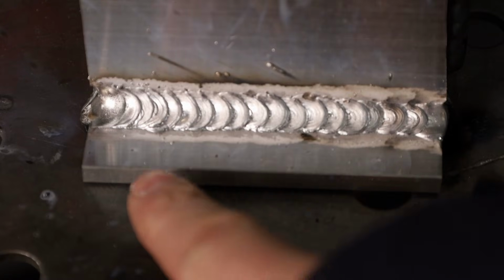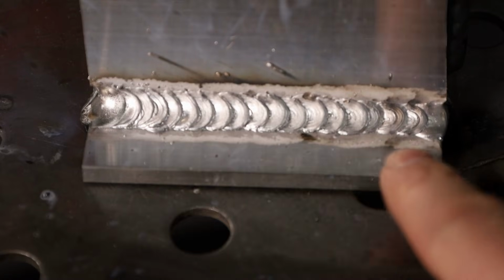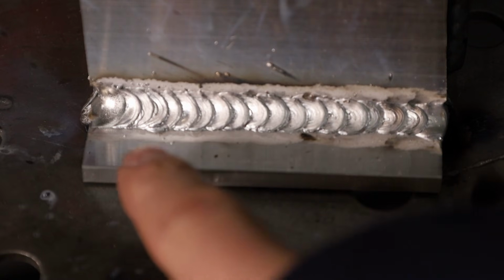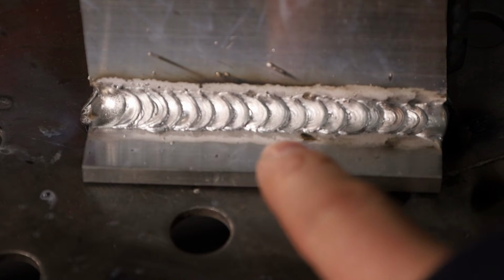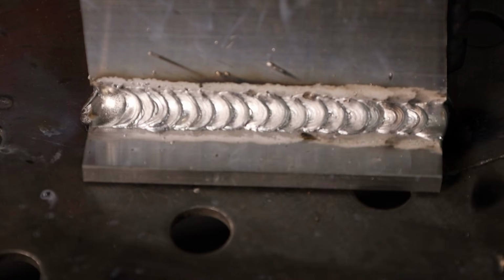So I'm using that 5/8 to 3/4 inch stick out, push angle to keep gas flowing up ahead of me. It's shielding really nice. This is no cleaning. There's almost no soot there on the weld, a little bit outside of the weld zone of that black deposit, but real nice. All right, well, there you have it. We put this thing through its paces.